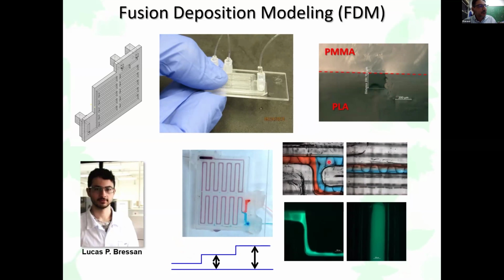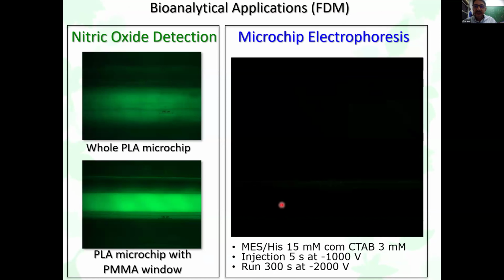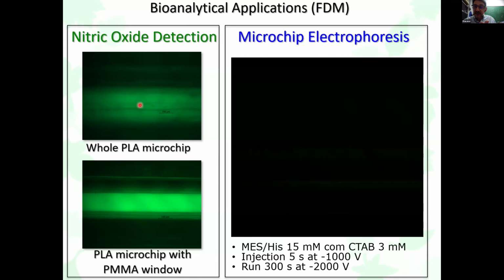This is a photograph of the mixer just here at the confluence, and also far from the confluence, showing the mixing. Here is the same mixer, but using a fluorescent solution. So you get the fluorescence here, far from the confluence. Here you can see the difference between a device prepared completely sealed, on the top here, and the device prepared over the PMMA substrate. So you can see the channel inside the device much more clearly. And here is a separation. You see it passing here. This is a fluorescent compound moving through the electric field for separation using capillary electrophoresis on this device.